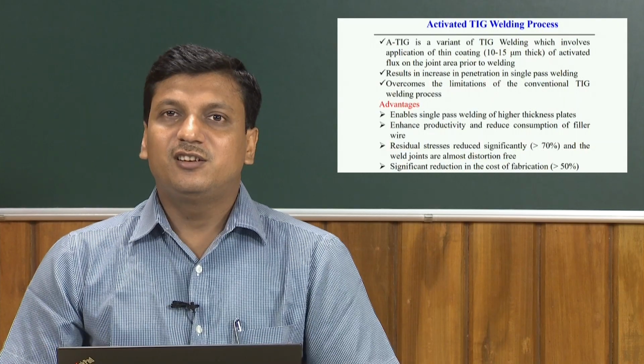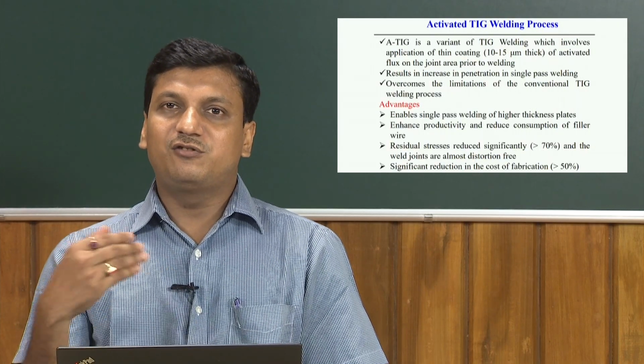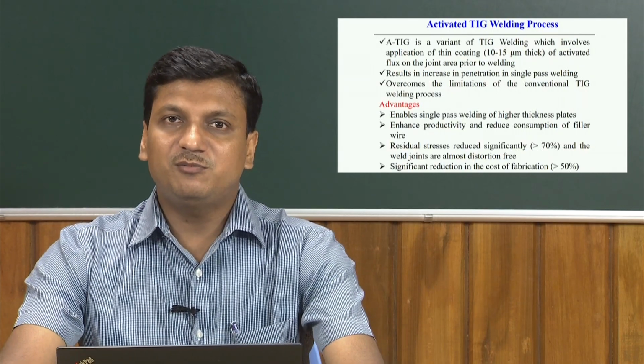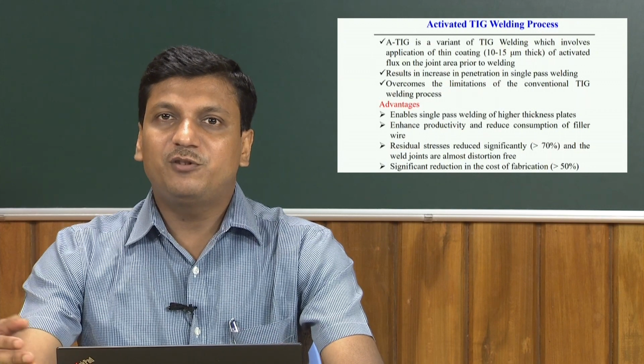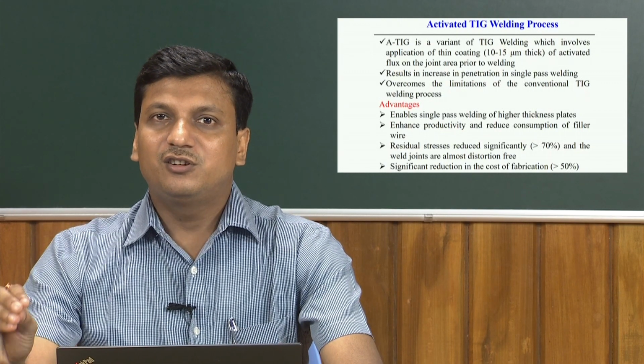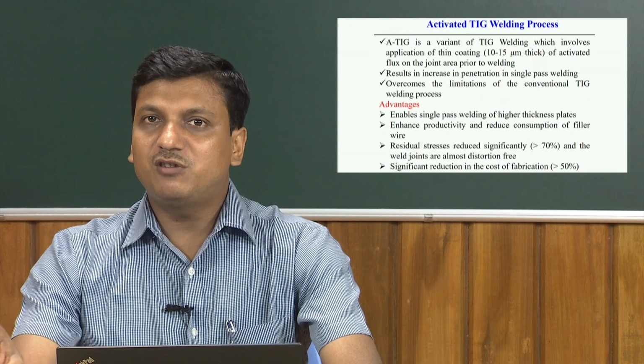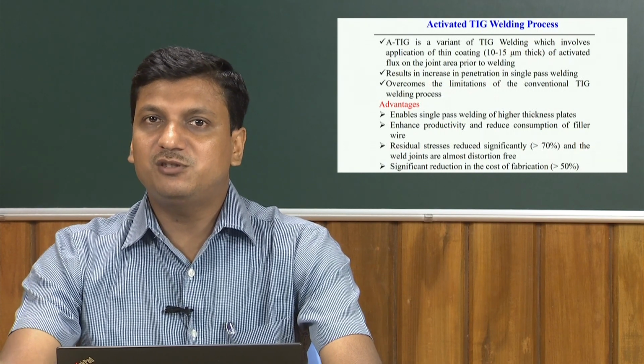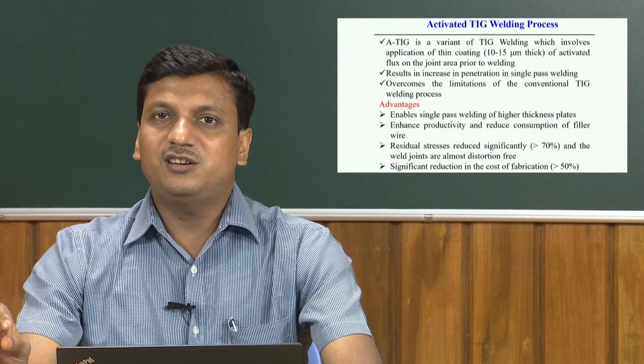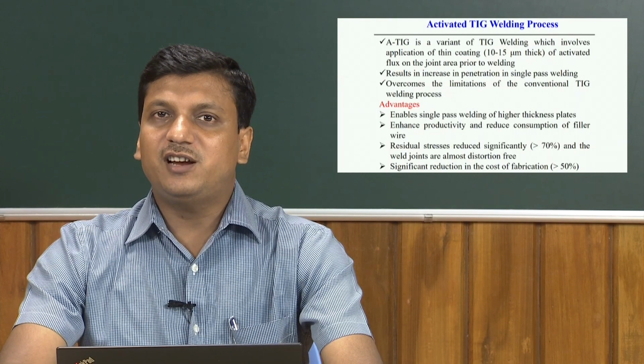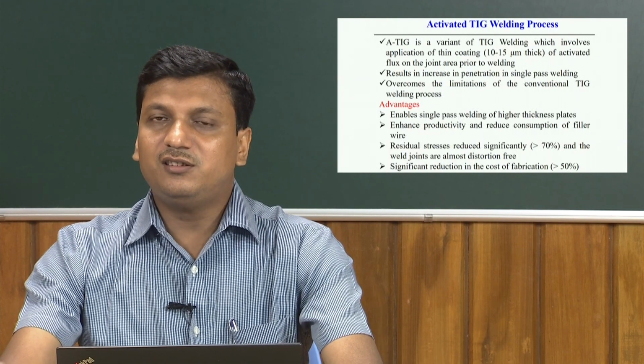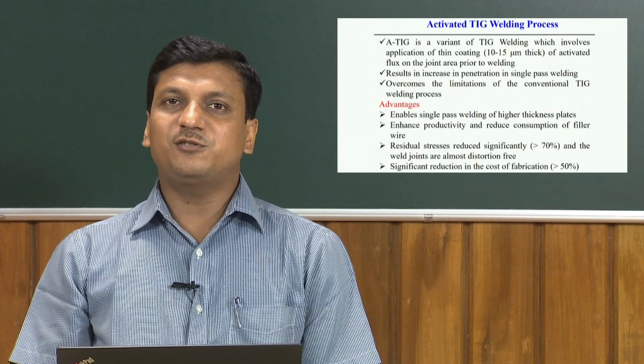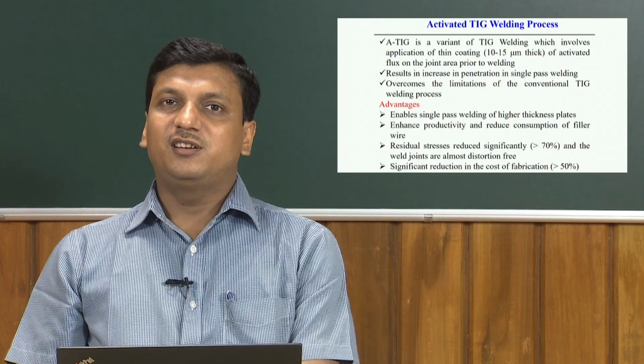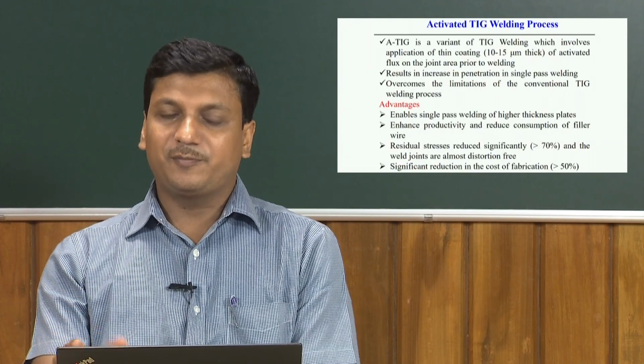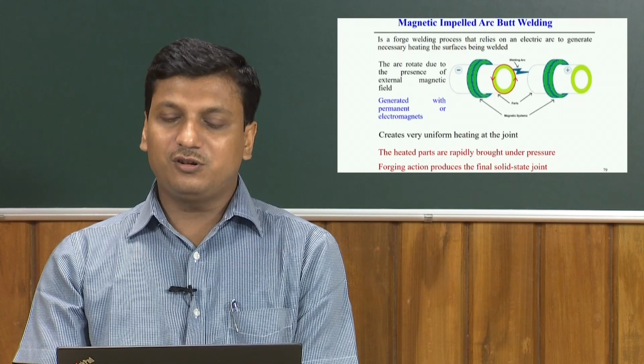But practically, when you try to incorporate the effect of the surface active elements, a prior investigation is required to find out the optimum quantity of the surface active elements for a specific welding system. That is important to know, because at any quantity it may not be possible to achieve the effect of the surface active elements positively.